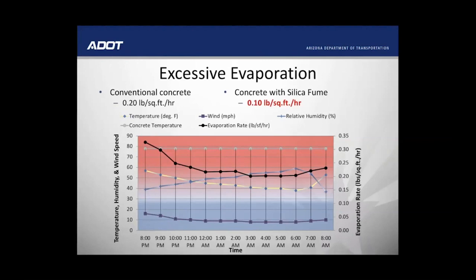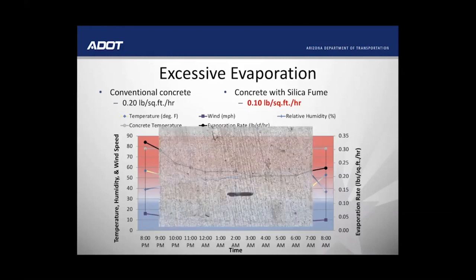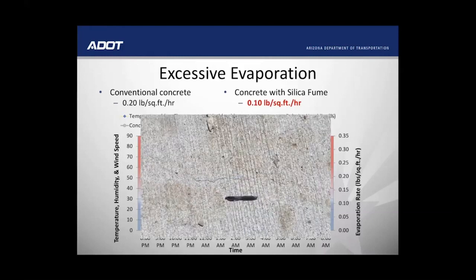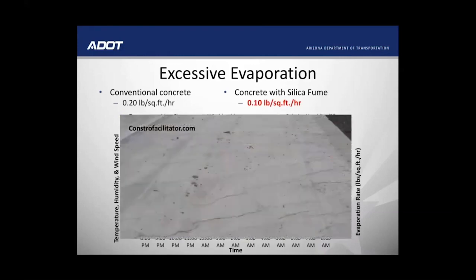If you test her, she'll bite you every time and give you these. That is a plastic shrinkage crack. If you ignore her altogether, she'll give you more of these. Now this isn't the concrete mixture's fault. It's a result of poor conditions and poor coordination of placement, finishing, and curing the concrete.